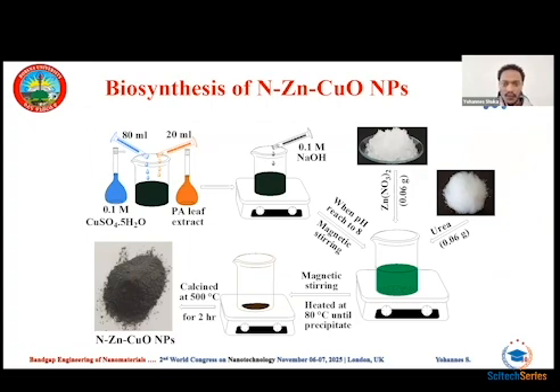The modification of copper oxide nanoparticles with nitrogen and zinc was conducted by applying the same experiment, but with the addition of two precursor sources, that is zinc nitrate and urea, as the source of nitrogen, at the stage of solution mixture. Then the precipitate was also transferred into a furnace for calcination, which is used to remove organic contamination from the nanoparticles, at 500 degrees Celsius for 2 hours. After that, we obtain the gray nanoparticles, which are nitrogen-zinc-codoped copper oxide nanoparticles.